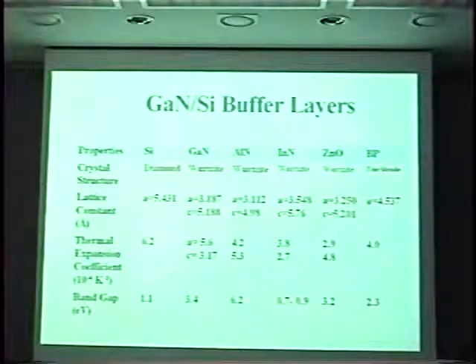We've also looked at trying some other buffer layers. Now that, by the way, was gallium nitride grown directly on silicon. There was no intentional buffer layer placed there. That gallium nitride, I believe, is the highest quality gallium nitride that's been grown directly on silicon to date. It has a full width half max on the high resolution XRD 400 reflection of about 800 arc seconds, so dislocation densities on the order of about 10 to the 7 per square centimeter. So for direct growth of gallium nitride on silicon, it's considered very high quality material. It's the highest I believe it's been grown.